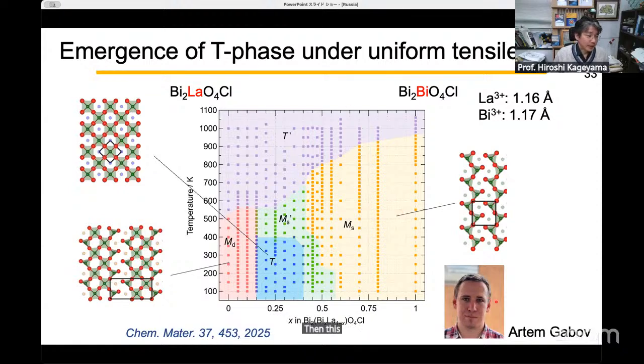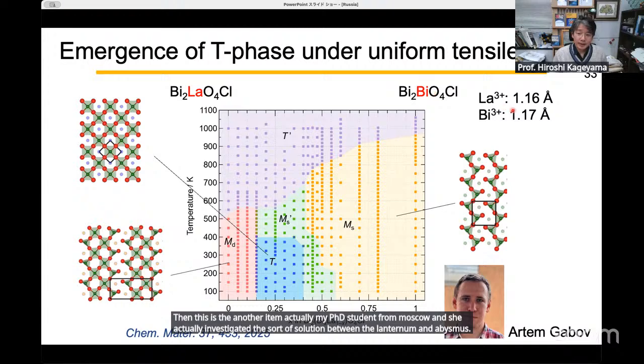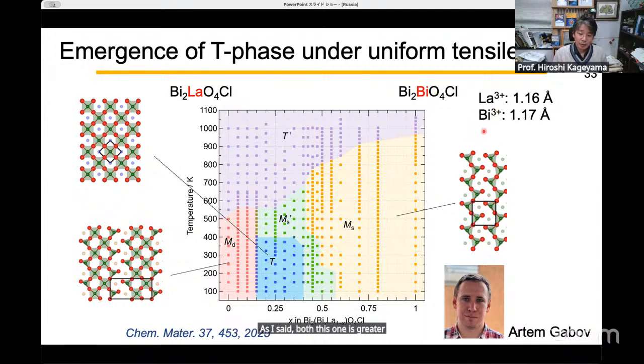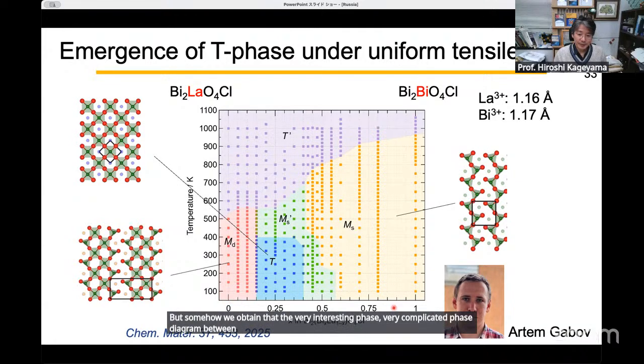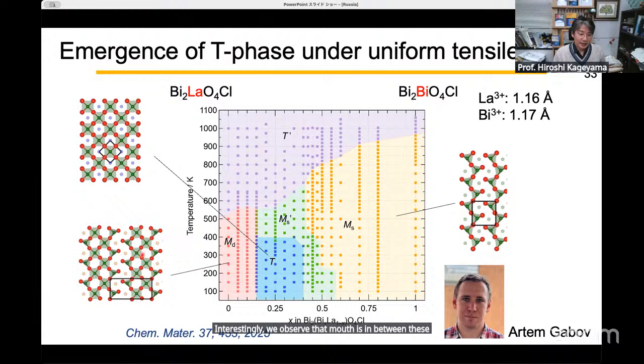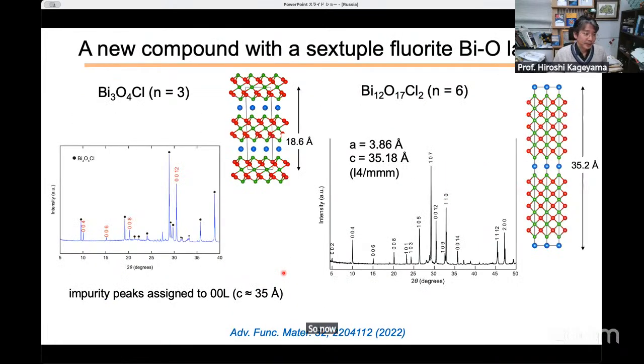Then this is another atom, actually my PhD student from Moscow, and he investigated the solid solution between lanthanum and bismuth. As I said, this one is greater than Bi3+, but these two species are very similar in size. But somehow we obtained a very interesting, very complicated phase diagram between lanthanum and bismuth as a function of temperature. Interestingly, we observe a tetragonal phase in between these chain structures. So maybe these two chain phases somehow compete with respect to each other to form the non-broken ideal square lattices.